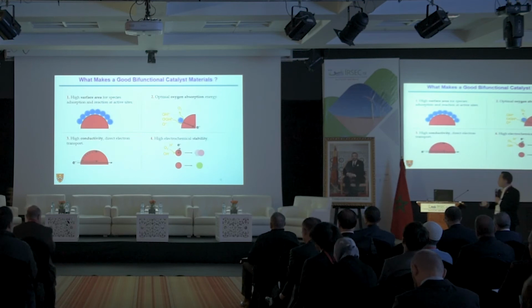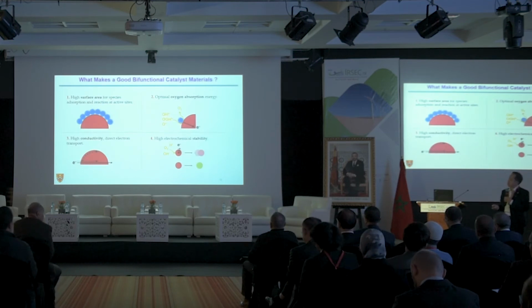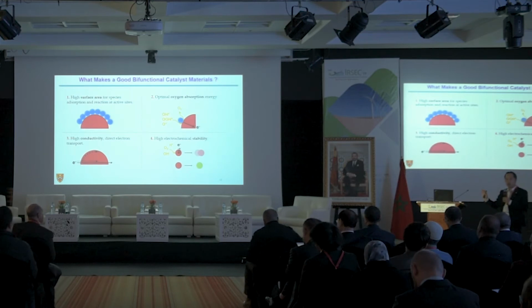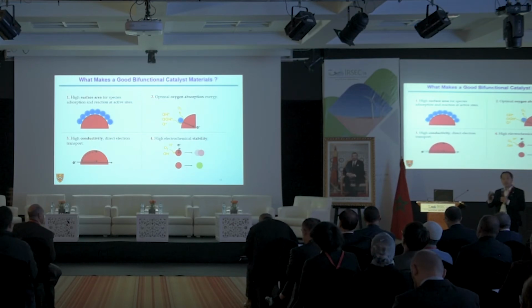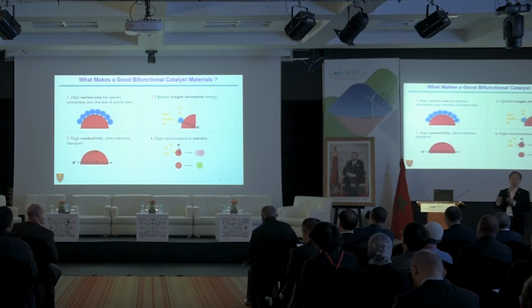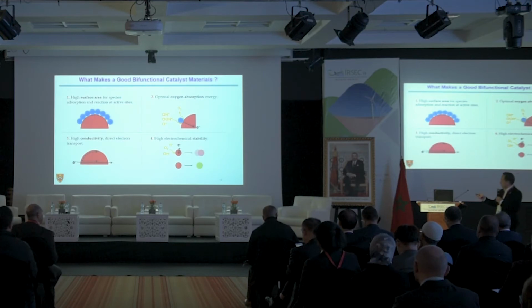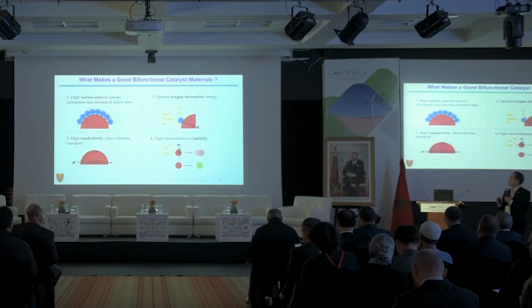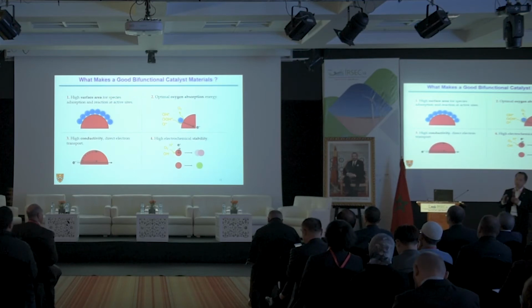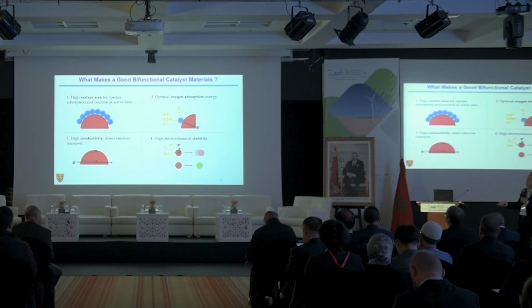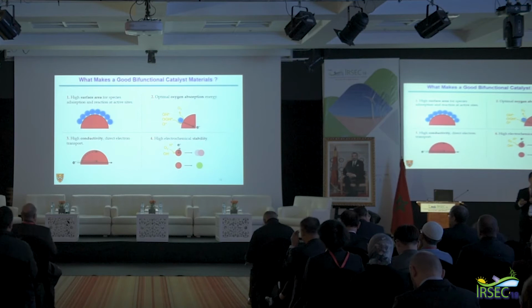So when we try to design a good bifunctional catalyst, as we know, we have these 4 parameters we need to be careful. One is we'd better have a high surface area catalyst so that you have enough active sites available during operation, right? Second is you'd better have an optimal oxygen adsorption energy because this will relate to your kinetics very closely. And then number 3 is, for all the electrochemical catalysts, you'd better have very high conductivity. With this high conductivity, you make this reaction easier.